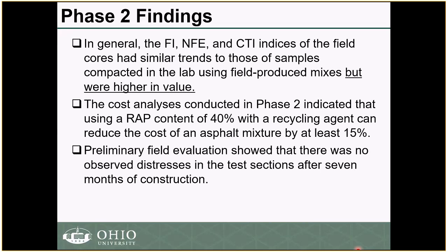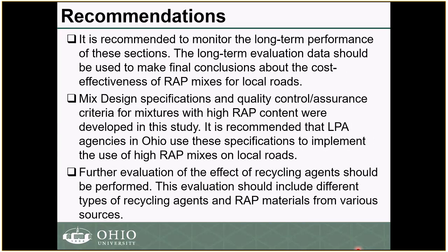A preliminary evaluation that we have conducted so far is indicating that there are really no issues with the test sections after 7 months of construction. So what are we recommending? Again, we only monitored those test sections for 7 months. This is not enough really to draw any conclusion. So what we are recommending is that those sections have to be monitored. We have provided in our report a methodology for monitoring those test sections. I would say that those test sections should be monitored for at least 5 years. And then based on that, you can draw conclusions about performance and also about the cost effectiveness of increasing RAP.